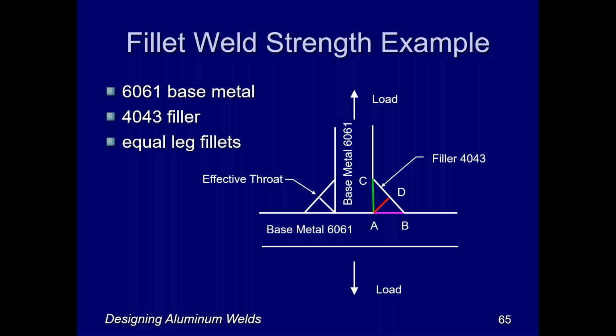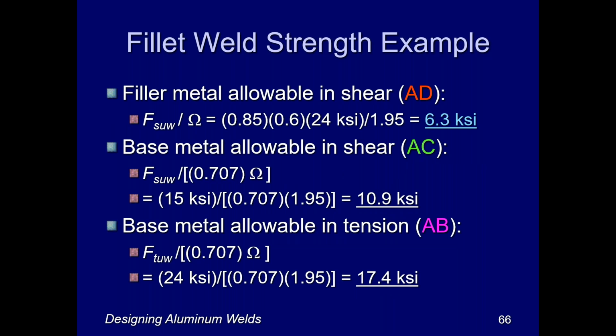And we would calculate the stress on each one of these, and we could determine which one was the least. And we're typically going to find, and in almost all cases we'll find, that the filler metal allowable is the governing strength of the joint. It's 6.3 KSI, whereas we have stronger strength of the base metal in shear and stronger yet in tension. And of course, we would expect that because tension strength is always greater than the shear strength.